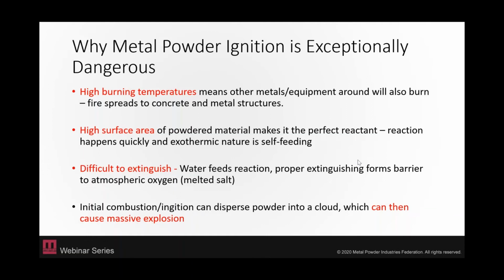So this reaction will happen very, very quickly, and it's exothermic in nature, so it's self-feeding. That is an important thing to understand. Once a metal powder fire gets going, it's almost impossible to put it out. So that's the next point, difficult to extinguish. If you put water on this, that's probably the worst thing you can do, because as we said before, in water atomization, the water actually supplies oxygen to the metal. The metal will rip that oxygen right out of that water molecule, and you will just make things worse. So one of the ways to properly extinguish a metal fire is a salt extinguisher. This salt will deposit over the metal fire and it will melt and isolate that metal fire.